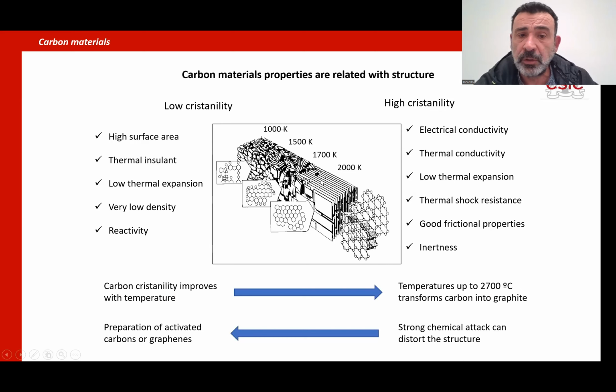Some materials with low order, when they are treated at very high temperatures, nearly 3,000 degrees centigrade, they transform into graphite, and you can break down the graphite by a strong chemical attack. For example, this is what we do to produce graphene oxide. You can disorder the material by a chemical attack. Okay, and that's everything you have to understand.